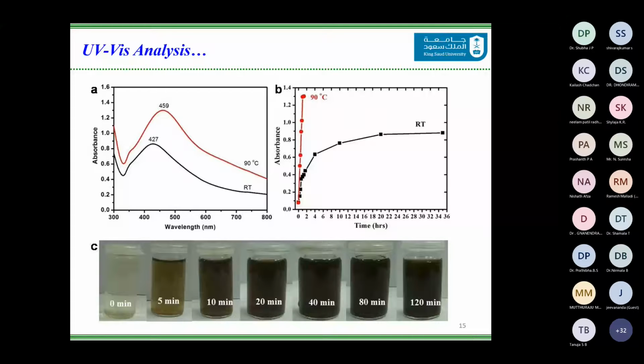However, if you look at the next graph, you can notice that when the reaction was carried out at room temperature, it took 36 hours for us to get the desired product. While when we did the same reaction at 90 degrees centigrade, the reaction was complete within 2 hours. And below, I would like you to see how the color is changing with time. In 2 hours, we get a solution that is dark enough, and the formation of the nanoparticles has been confirmed by UV.